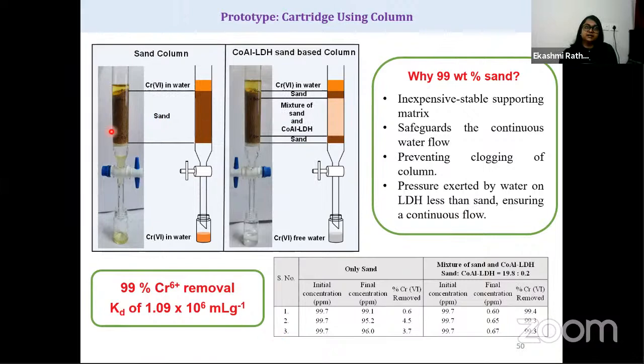So we found from our column studies that we were able to remove 99% of chromium, with a very high distribution coefficient.